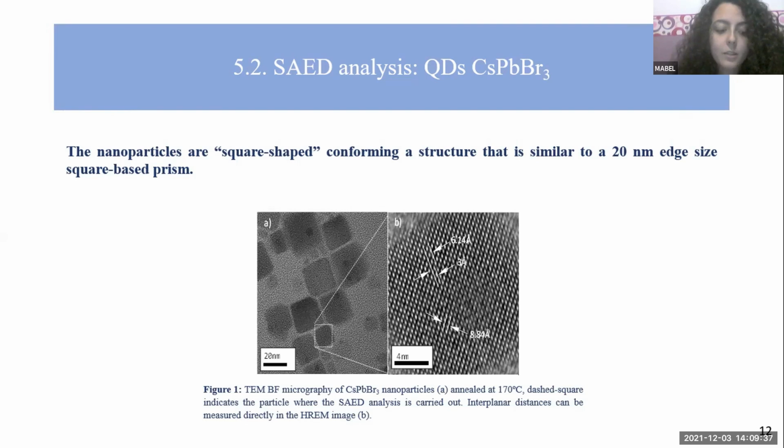To distinguish well-aligned nanoparticles, high-resolution transmission electron microscopy images were acquired for a variety of nanoparticles, shown in Figure 1B. We consider that a nanoparticle is well aligned when atomic columns can be appreciated and the fast Fourier transform shows a comprehensible pattern.